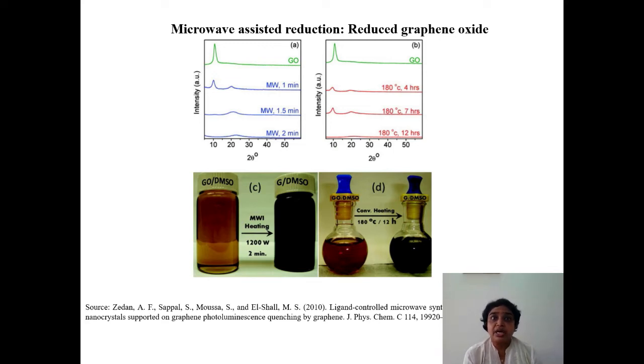under microwave radiation at 1200 watt power is even much higher than that of the sample derived, if you see, this is a sample which is prepared through the conventional way in 12 hours, and if you compare, this is your starting graphene oxide. So in just 2 minutes, the entire graphene oxide is reduced to reduced graphene oxide. However, in the conventional method, it took 12 hours, and just imagine how much energy consumption was there. On the contrary, microwave just in 2 minutes gave the same result.